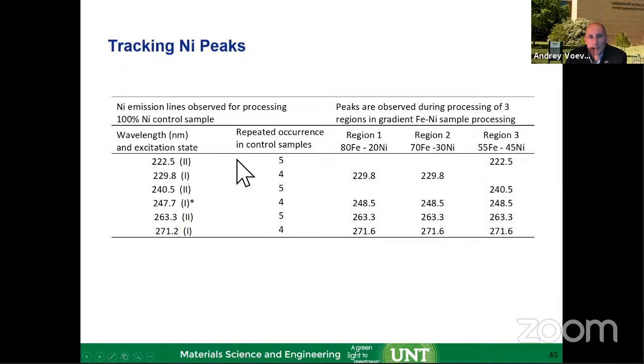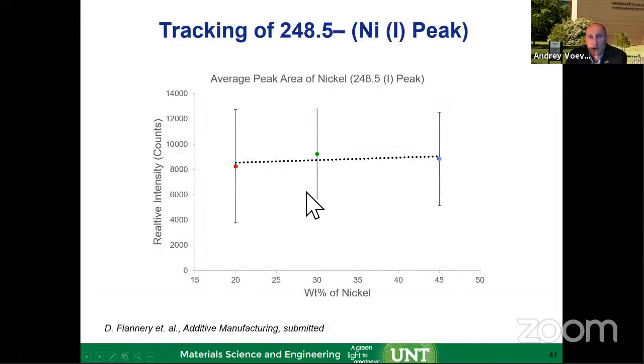All right, so looking at the nickel peak, we also find those characteristic nickel peaks that compare well to the NIST databases for the nickel excitation. Again, that excited peak seems to be appearing, and a few others appear through all the regions. When we plotted the nickel peak, our error bars got even larger. So we are changing the nickel composition here, and we don't see much of a spectroscopic signal within the error bars; it stays flat. So we cannot conclude anything, either increasing or decreasing, on the nickel peak, even though we know that during the build we were changing the nickel composition as we go.